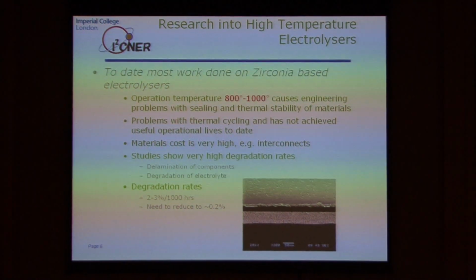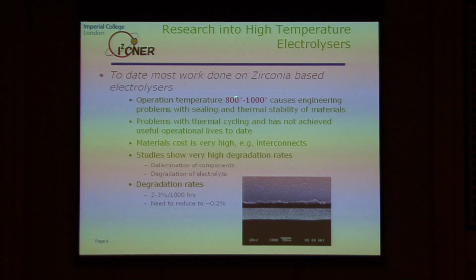There has been some research so far into high temperature electrolyzers, mainly on zirconia-based systems, which means the cells must be operated in the temperature range of 800 to 1,000 degrees. That causes engineering problems in fabrication, including sealing at high temperatures, thermal stability of materials, and problems with thermal cycling up and down. No one has achieved useful operational lives with thermal cycling so far.